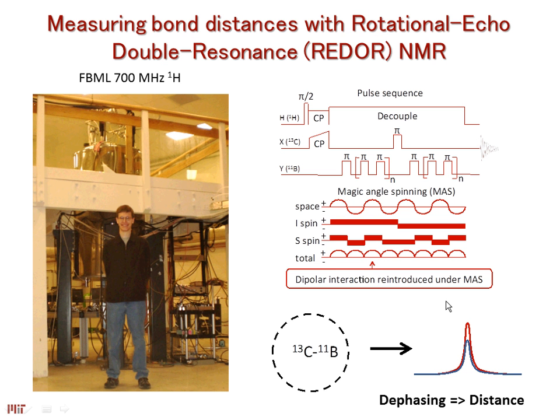These are called rotational echo double resonance techniques, and this has to do with establishing a very clever pulse sequence to eliminate and then reintroduce dipolar coupling, or dipolar interactions, in the particular nuclei that you want to investigate. And by doing this pulse sequence that introduces in a very systematic manner this dipolar interaction, you can start measuring distances between the two nuclei over here.